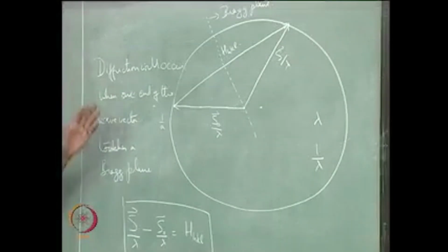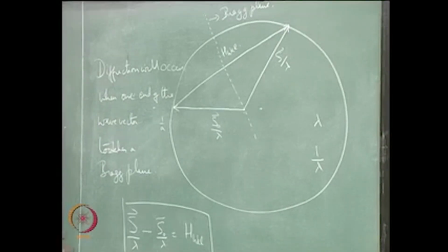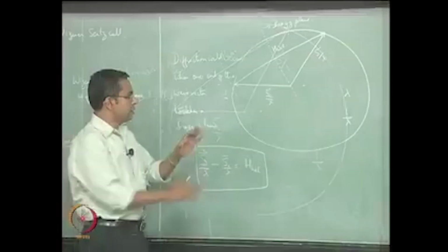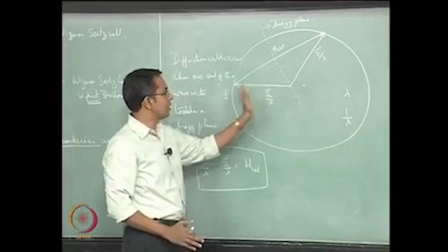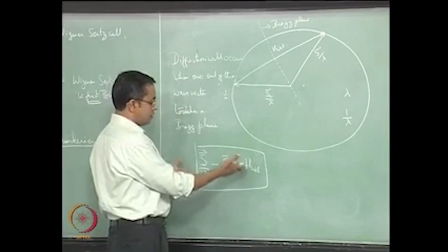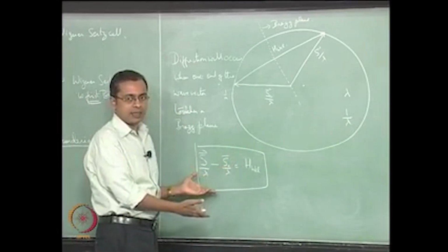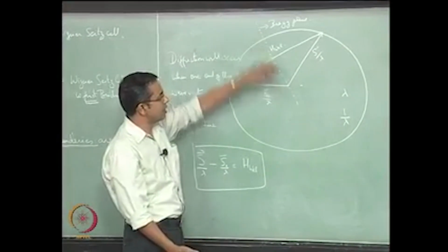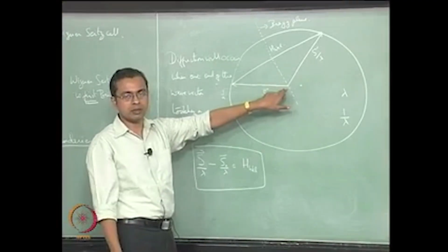Okay. So I have just restated the definition, or rather described it in a different way, because we find that this is true. We find that whenever you draw this diagram, whenever this equation is satisfied, which always represents the diffraction condition, the diagram shows us that if you draw the perpendicular bisector of HKL, it will show up going through that point, right.